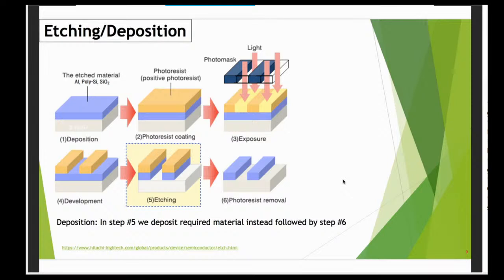Another thing is, instead of etching, you can deposit material, right? You need metal to be deposited to make contacts. So the principle is the same. You can either do electroplating and then dip it into a solution to remove the resist that is left over, so it will remove any metal that is not intended, or you can do an evaporation of the metal onto the surface in a vacuum chamber, and after that remove the resist, and what you're left with is the final pattern printed onto the semiconductor wafer, either in the form of an etched surface or in the form of deposited materials like metals or even oxides and so on.